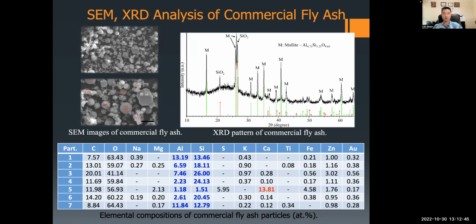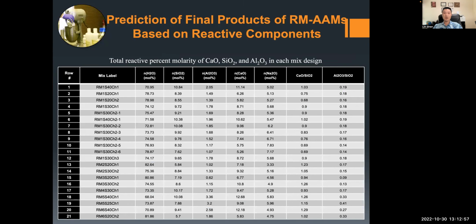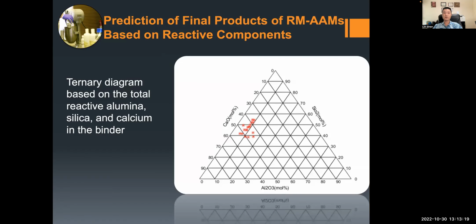And here shows commercial fly ash. It has a classic spherical shape, much higher quality, very reactive phases. And here shows the major reactive phases of different types of raw materials, including reactive calcium oxide, silica, and alumina. Based on that, we can predict the final hydration product of the concrete based on these components. And also with the help of this ternary diagram showing us the percentage of reactive calcium, silica, and alumina.